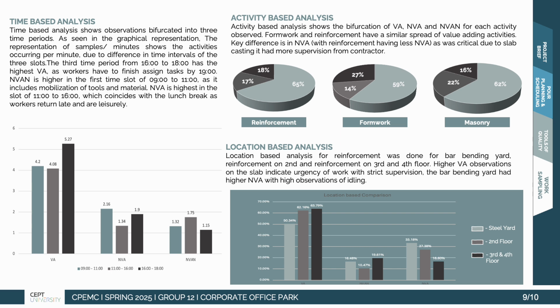So for time-based analysis, we bifurcated the observations into 3 time periods, which were 9 to 11, 11 to 4, and 4 to 6. And as seen in the graphical representation, we prepared a graph of samples per minute due to the time difference and time intervals of all 3 slots. And the graph shows that the third time period of 4 to 6 has the highest value adding activities, whereas the workers have to finish their assigned tasks by 7 p.m., so they are rushing to finish work.